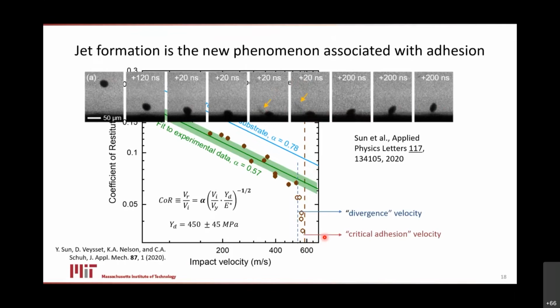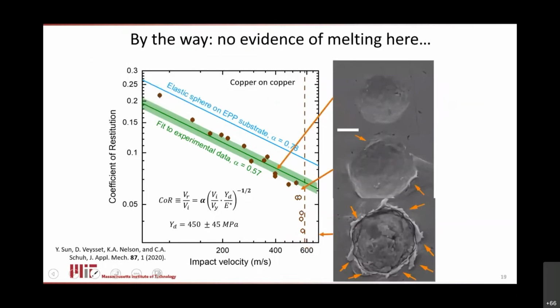So there are two critical velocities now that we can measure, and these are independent measurements, by the way. This is important. We can measure the velocity at which we start to diverge from plasticity, and we can measure the velocity at which particles cease to bounce at all. So we have two different critical velocities that we can now measure and study. I'm going to mention something important before I go on here.